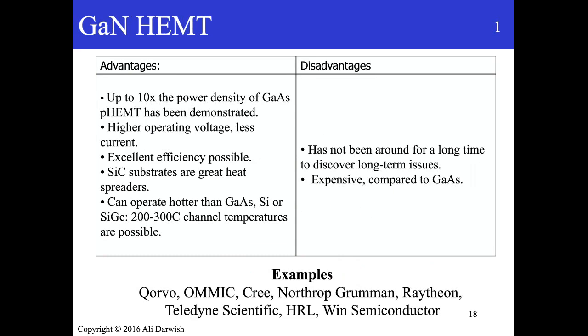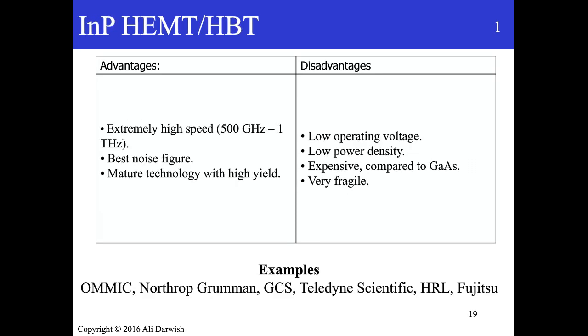process. Gallium nitride, on the other hand, is very high power. It can reach high temperature and still perform excellently. And at this point, many foundries offer it, and it's quickly replacing gallium arsenide. Indium phosphide, as I mentioned, is very high in speed and offers some of the best noise figures that we can get out of any mature technology.